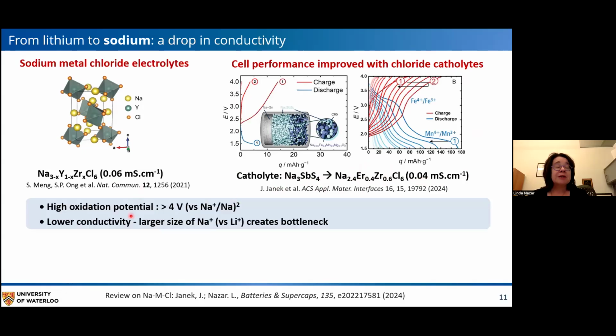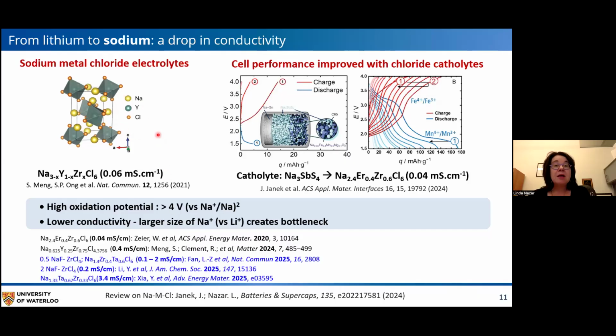So just like in the case of the lithium halides, these have a high oxidation potential, which is very beneficial. But as I said, they have lower conductivity. And in great part, this is because of the larger size of sodium compared to lithium, which creates a bottleneck, in particular for crystalline structures. So the first few of these that were reported, the one mentioned here, and also a variation on sodium zirconium chloride with a higher conductivity. As I said, these are all crystalline materials.